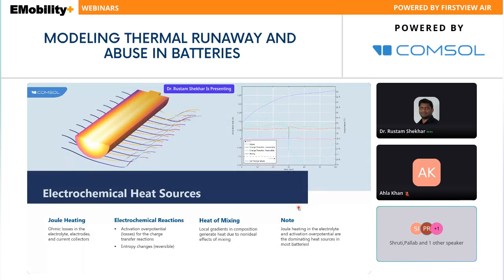So which losses will couple batteries and heat transfer? Here you can see the Joule heating, the electrochemical reaction heat, and the heat of mixing. All three losses we can see and then plot them separately. Once you know which losses are dominating, then we can work accordingly. So let's say if your Joule heating is more, that means the conductivity of the electrolyte and the solid parts that we are working with is less. Then we can work on the Joule heating part of it.